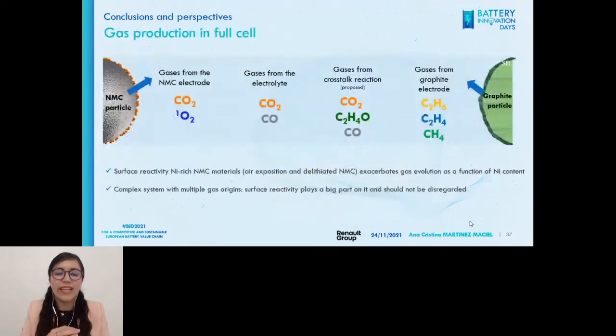Then regarding the gas, we saw that the surface reactivity of the nickel-rich NMC exacerbates gas evolution as a function of nickel content. This is especially true for the highest nickel content materials, and this is a complex system. There are a multitude of gas origins, as I've enumerated here, and they should not be disregarded. We should always consider each of the different gas sources.